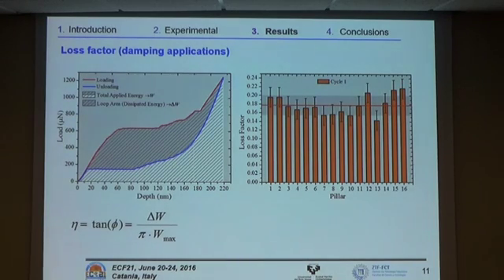And since damping capacity was claimed as one of the potential applications of this type of material, we studied the loss factor, which is defined according to this equation. Basically, this is the area of the cycle over the total area times pi. And we determined this loss factor for the 16 pillars after the first cycles. And first of all, I have to point out that the loss factor for metallic materials in this case is quite high. It's very good damping capacity. And this is for the first cycles.